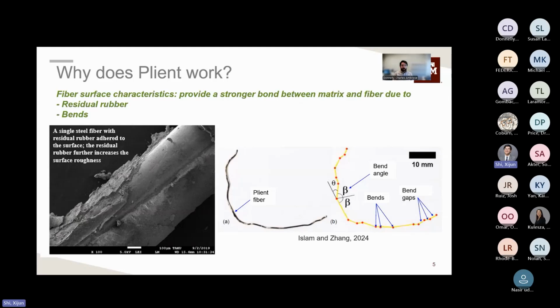And then the other reason that the fibers work well is because of the bends in the fiber. Because of the natural recycling process, the fibers do not come out straight. There's some angularity to it, and these bends vary between the fiber lengths. But the important thing is that both the surface texture from the residual rubber and the bends improve the interface between the fibers themselves and the surrounding cement matrix.